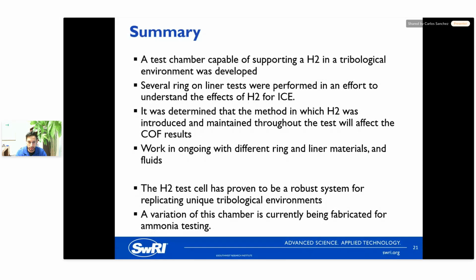One thing we didn't really study, and I didn't present here, is the effect of condensation or water, but we did do some of those tests, and they'll probably be presented at a later talk. Like I said, work is ongoing to test different ring and liner materials and different fluids that may be formulated to better support the hydrogen environment. But overall, our test cell has proven to be fairly robust. What's good is that it's a fairly large chamber that can do ring and liner experiments as well as other test geometries. It's fairly reliable, fairly repeatable. And right now, we're actually working on a variation of this chamber that's able to support ammonia testing. So look for that coming pretty soon.